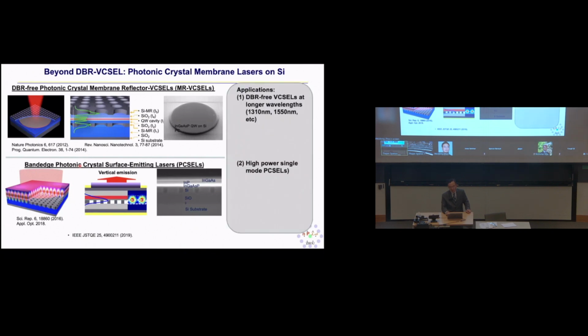And the application is you can also design so that your VCSEL can be long wavelength, because one of the limitations for DBR-based VCSEL now is mostly at the gallium-arsenide-based 1 micron. You still can do any wavelengths. You are not limited by your DBR anymore. So you can really go onto any material for different wavelengths. And also, as I already mentioned earlier, this kind of structure can extend to high power as well for high power PCSELs. So that's one application, using the reflector property principle here.